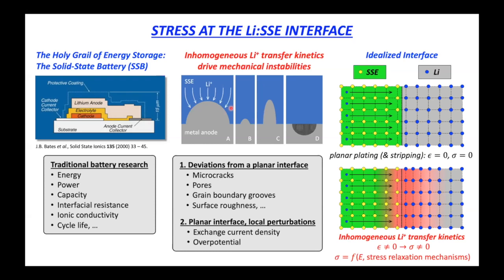And so the upshot for us here is that these lithium-filled interface defects create a local gradient in the chemical potential, and that gradient forces the incoming lithium ions during charging to preferentially plate out into these defects, right? And as that happens, the pressure in these defects basically just climbs, right? And so it creates this mechanical instability that is thought to be the precursor to the formation and growth of lithium dendrites or filaments that originate at this interface and then work their way through the separator and cause the cell to short circuit.